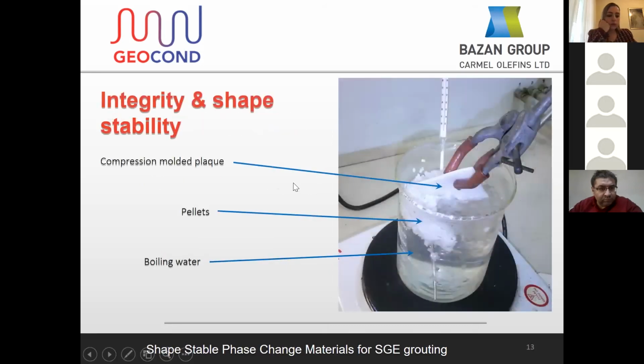On the other hand, if we take a pelletized shape-stable PCM containing about 80% of the same paraffin wax, and we put it into boiling water, here the water is boiling, we will see that the pellets stay pellets, the plaque stays plaque, both keeping their geometry and size, despite the paraffin undergoing a phase change, changing state from solid to liquid.